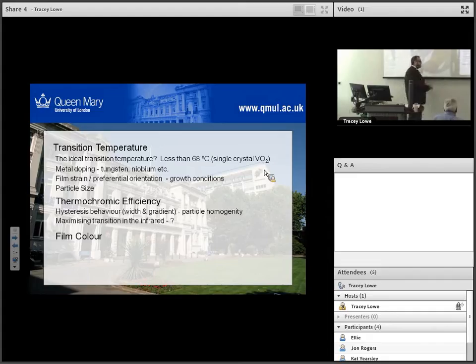We also have another issue. About 40% of our infrared radiation is going to come into our building, or from the sun, between 700 nanometers and 1200 nanometers. How do we maximize the transition in that part of the infrared? Because actually the bit between 1200 and 2500 nanometers is small. We can modulate as much as we like, but it will have very little effect.